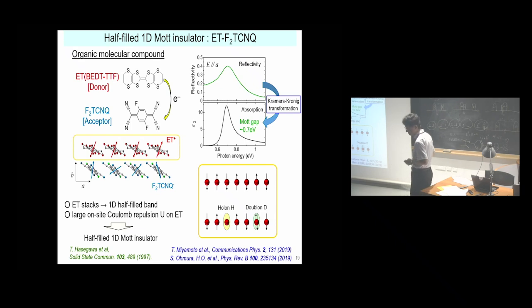Keeping these features in mind, we will discuss the previous result of 1D Mott insulators. The studied material is the ET-F2TCNQ organic compound. In this compound, an electron is transferred from ET to F2TCNQ. Each F2TCNQ molecule is almost isolated, and the overlap of pi orbitals exists only between the neighboring ET molecules. So, the 1D half-filled band of ET stacks dominates its electric property. Because of large on-site Coulomb repulsion U on ET, this compound is a half-filled 1D Mott insulator. In the absorption spectrum, a sharp peak due to the Mott gap transition is observed at 0.7 eV.